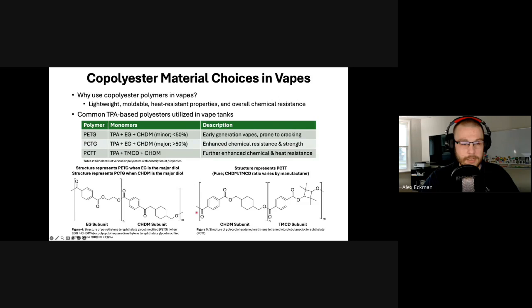And as we can see here, PETG was the early generation of vapes, more so in electronic cigarettes, and they were prone to cracking based on the different constituents of the e-juice, actually. So the industry switched to PCTG based on what they believed was improved chemical resistance and strength. However, that was still found to be a suboptimal polymer with potential leaching concerns.